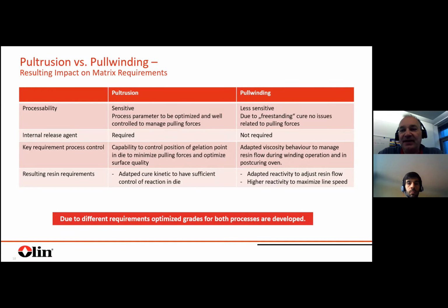On the pull winding side, for sure you also need an adapted reactivity, which is a little bit different from the pultrusion one, to control the resin flow in your process. And for sure, higher reactivity to maximize your output, so you have a little bit more freedom in the pull winding process. And this can be used to increase the line speed. For this reason, we as Olin have developed two different product lines, or different optimized grades, let's phrase it in these words, for these two processes. I will come later to this.